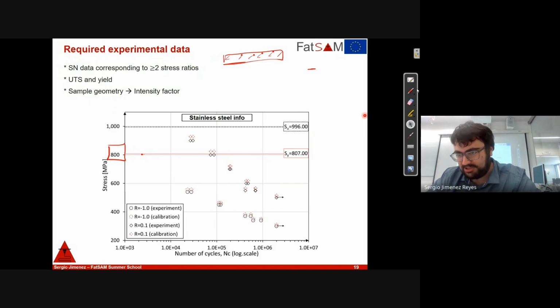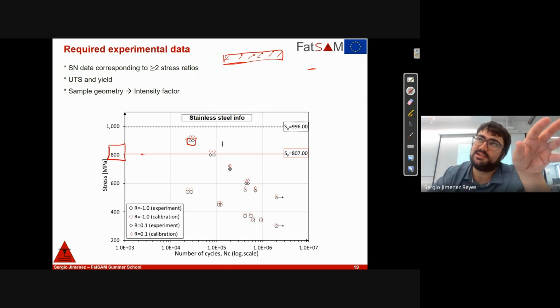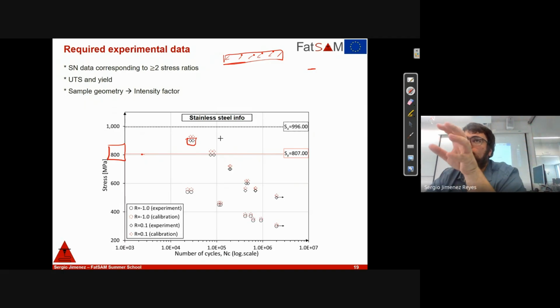What I'm saying here is, these are the stresses that the experimental people are reporting as maximum stresses, leading or driving to failure. This is a failure point. And what I'm saying is that the stress at the failure point, the point which is indeed initiating the non-linearities, is not this stress here. It is higher than this. So basically the calibration for your material, because you are not calibrating a sample, you're calibrating the material. You're calibrating the behavior of any point in this sample here.